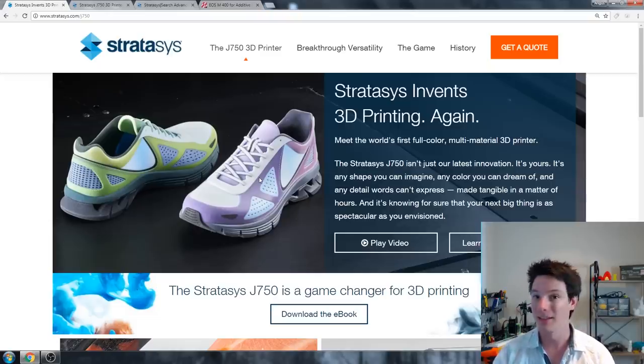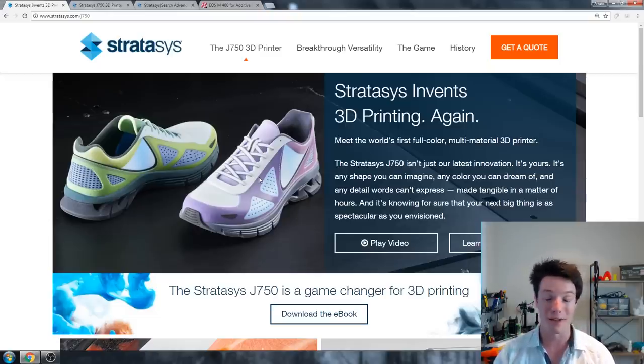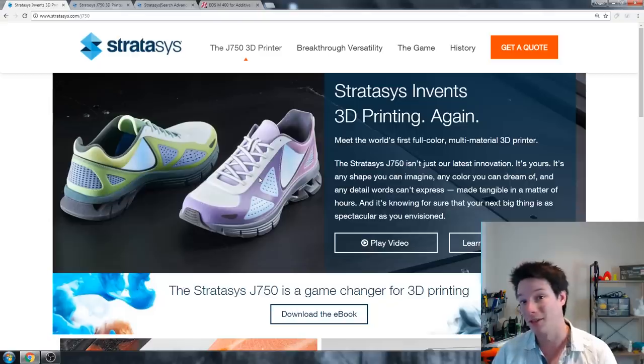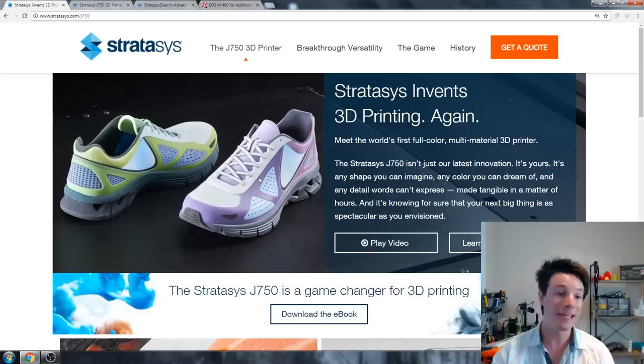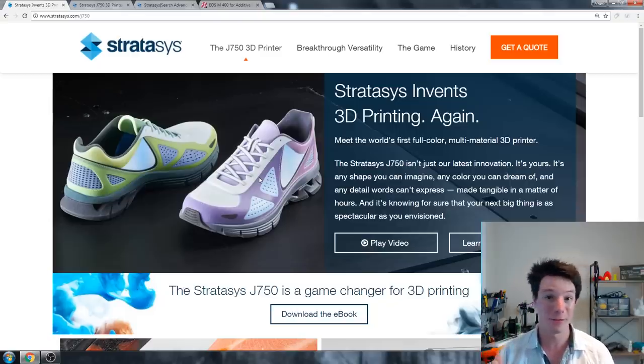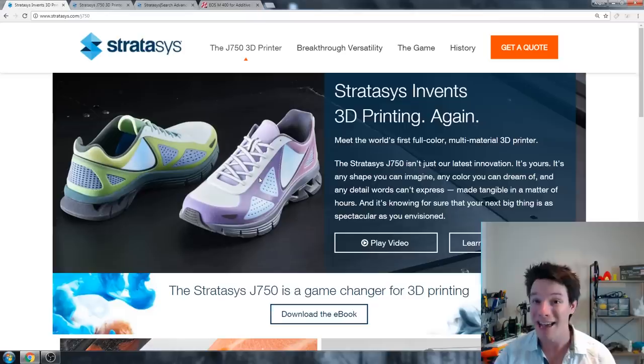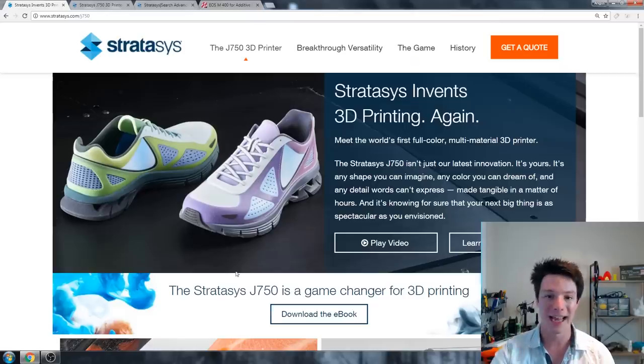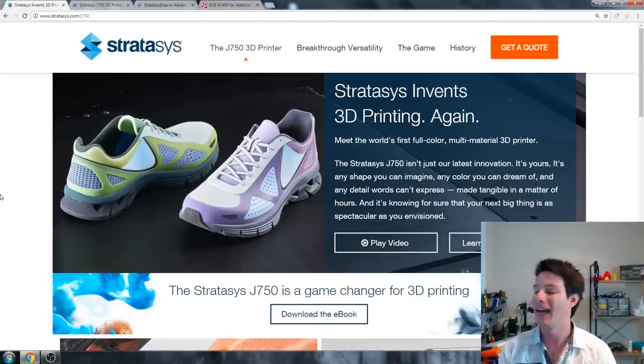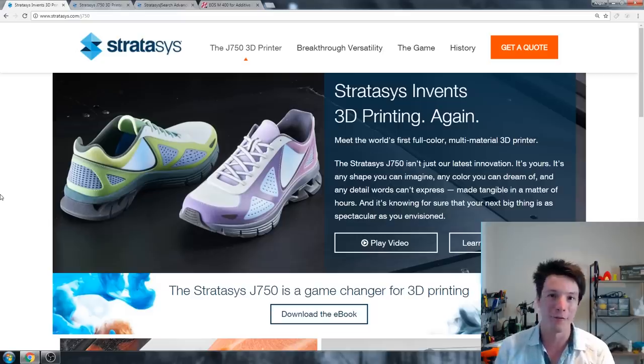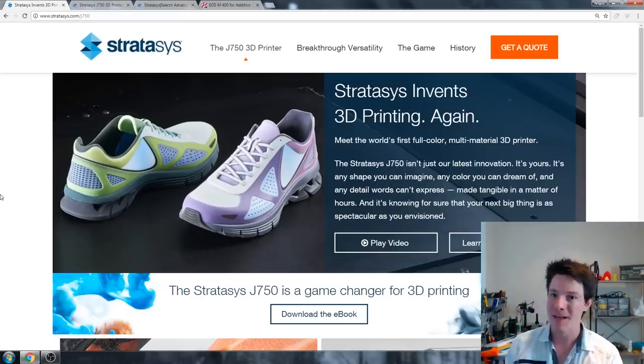Also worth noting that they also need support material just like FDM and SLA does, but you can actually use a jelly-like resin that jets in between all these layers. So they're not going to show it here, but they'll have a jelly-like resin supporting the layer above it, and then they use a water jet to wash it off. And again, these are UV cured materials, so they're not going to be great in sunlight and not going to last as long as the real deal.